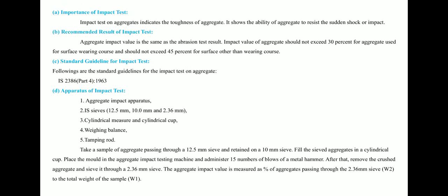Impact value of aggregate should not exceed 30% for aggregate used for surface wearing course and should not exceed 45% for surface other than wearing course. Again, the standard guidelines for impact test are given in IS 2386 Part 4, 1963.